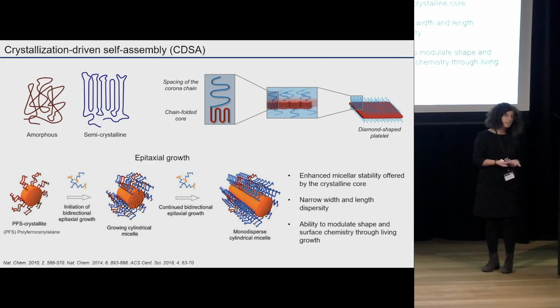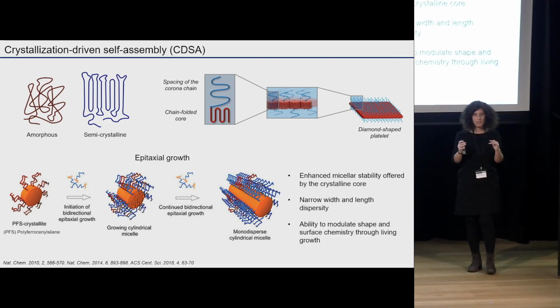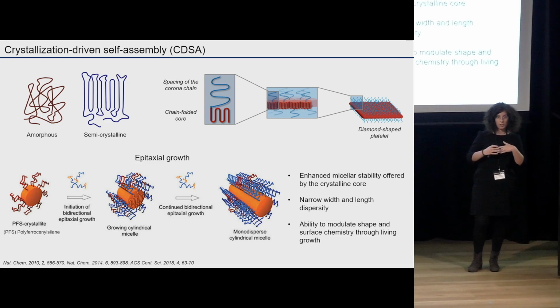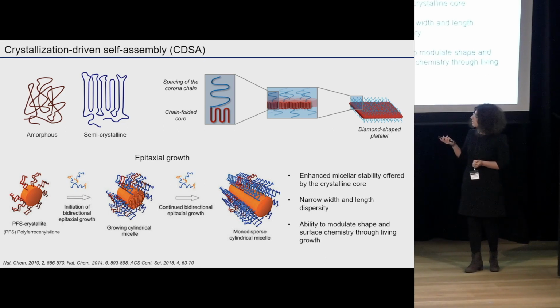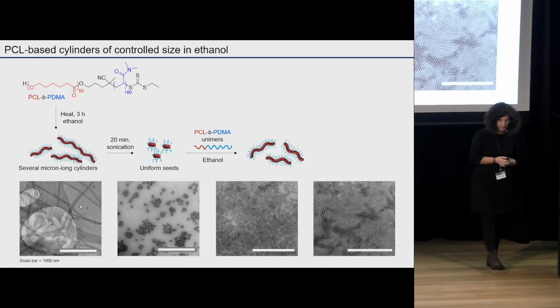Also, they have enhanced stability compared to other spherical micelles or micelle structures made from non-crystalline polymers. You can narrowly control the width and the dispersity. And also, and I'll show a little bit of this in my talk toward the end, you have the ability to modulate the nanoparticle surface chemistry. And so you have the ability to attach new functions to it and to create nanoparticles with multiple chemistries in it. So I'm going to tell you a few stories today, and the first one that I'm going to start with is this one here,